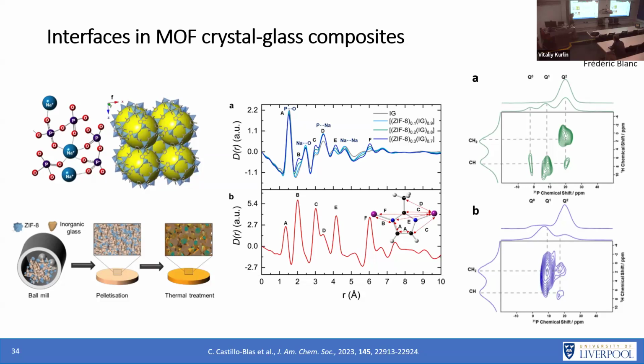And this was beautifully looked at in combination with pair distribution function. So this is a pair distribution function of the pure ZIF. We can see these atom-atom distances, so A to A here, whereas B to B here. So this is just correlating all of these distances, and then also the distances within the actual composites as well. So these are complementary techniques that are really useful not only for glasses, but you can also use them for crystalline materials as well.